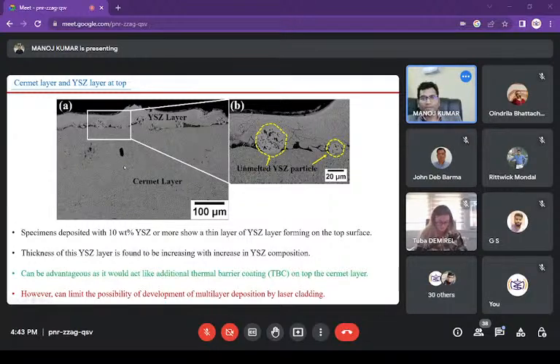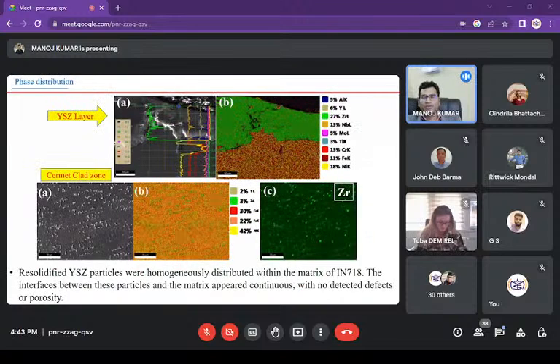So the problem does not lie only with the fact that we are not able to push all the oxides into the cermet layer, but also this extra deposition on the surface is hindering the next layer of deposition over this first layer of clad. So now we wanted to confirm this. So we did elemental mapping. So we can see that in the cermet layer, we have uniformly distributed fine particles of YSZ, and that is what we are looking for. We wanted that. But the problem lies over here.